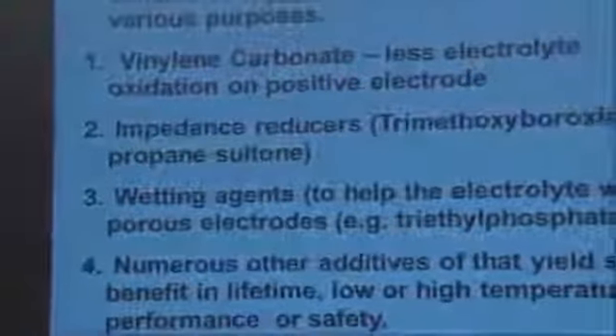All right, so now I want to use this equipment to start talking about, okay, lithium ions fail, well, what are we going to do about it? How are we going to make them better? And I want to talk about what are called electrolyte additives. So every lithium ion cell that you use, be it in your phone or in your laptop or tablet or whatever it is, the manufacturer has put in the electrolyte some chemicals like secret sauce that improve the lifetime of that cell. And they're called additives. And the most famous is vinylene carbonate, and it causes less electrolyte oxidation on the positive electrode, as I'll show you in the next few slides.